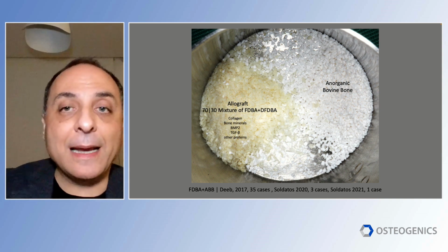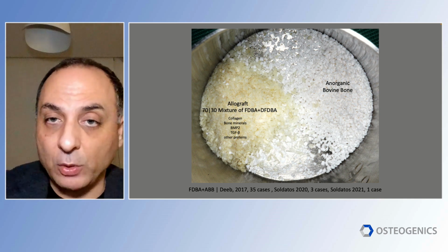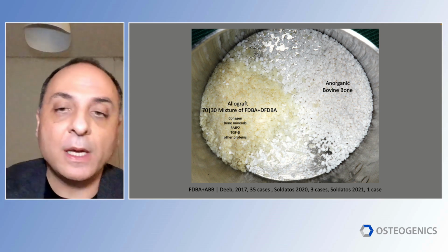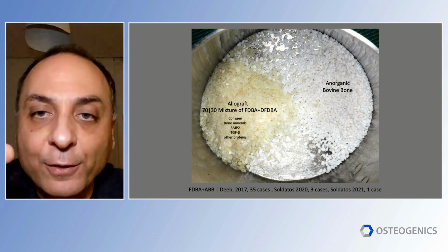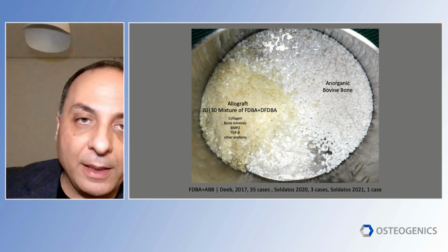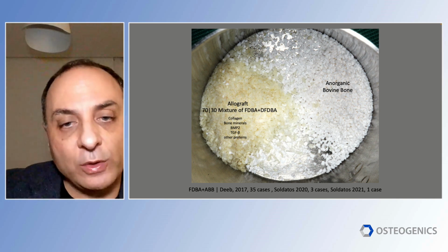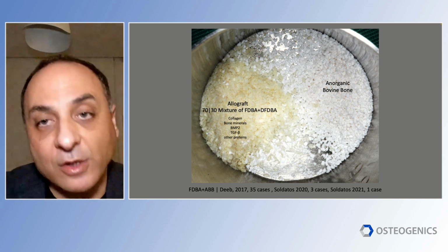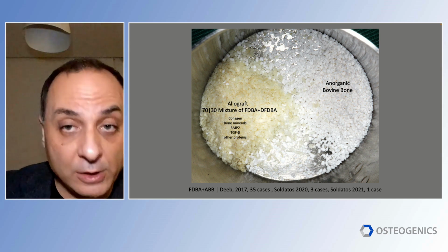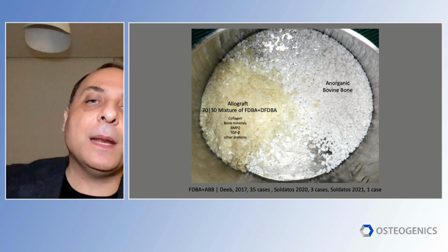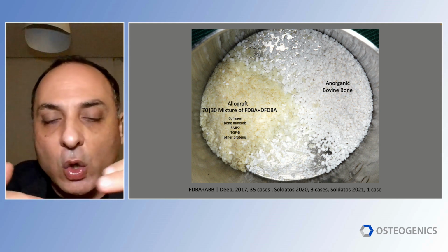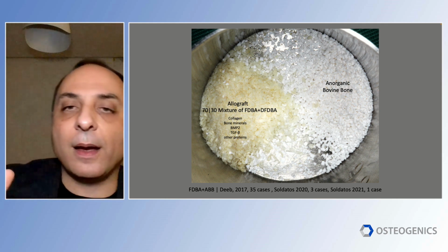Allografts, like autogenous bone, contain collagen, BMP2, and it was proven that they contain also TGF-beta and some other proteins. And in this graft combination, now we have 3 kinetics, 3 speeds. First, the DFDBA that resolves quickly, and it is osteoinductive. Second, the FDBA that has an average speed of resorption, and it's very osteoconductive. And then the bovine bone that's a good osteoconductive, and practically it does not resorb. So we have 3 different dynamics.